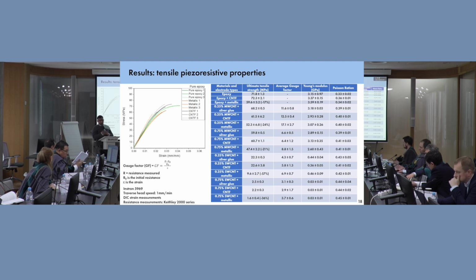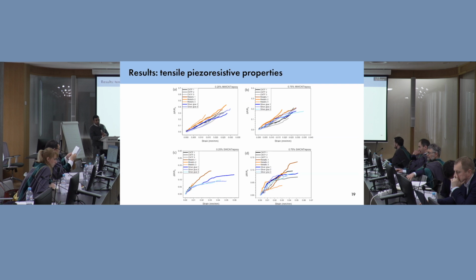Our Young's modulus also started to drop, as we see, meaning that our stiffness was decreasing, and our gauge factor makes a good correlation with what we see in literature. For our more resistive composites, we have higher gauge factors. For our more conductive composites, we have lower gauge factors. Again, it goes to percolation network and how much it's changing during the application of strain.